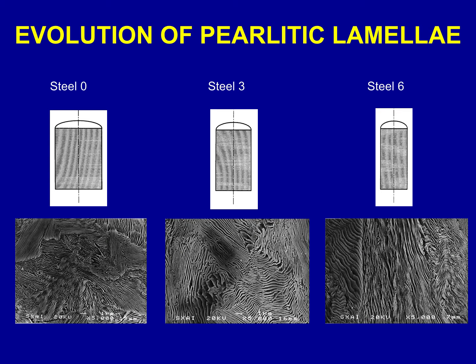The pearlitic lamella also evolved with cold drawing from a randomly oriented microstructure in steel 0 to a heavily oriented, markedly oriented microstructure like a microcomposite, nanocomposite, like a laminate in steel 6, in which the lamella are almost fully oriented in the vertical direction of the y-axis or cold drawing direction.